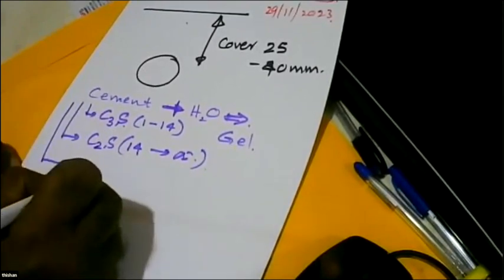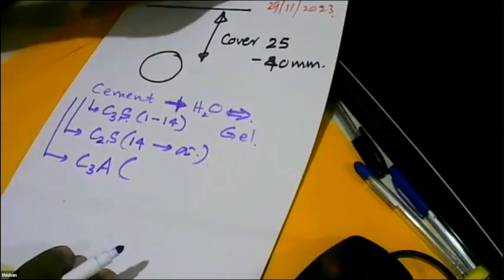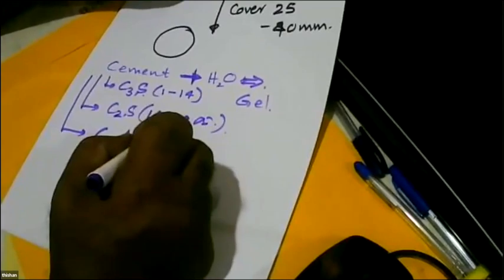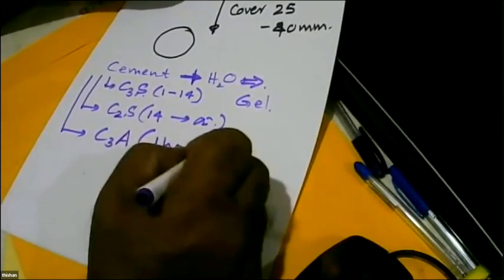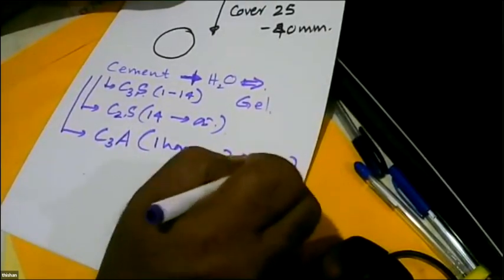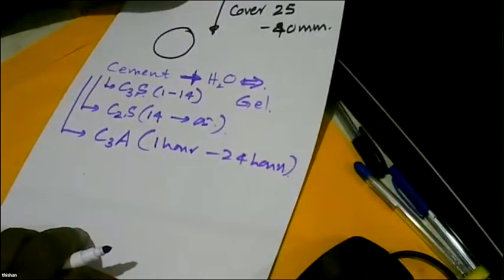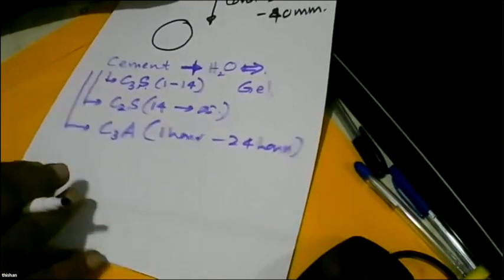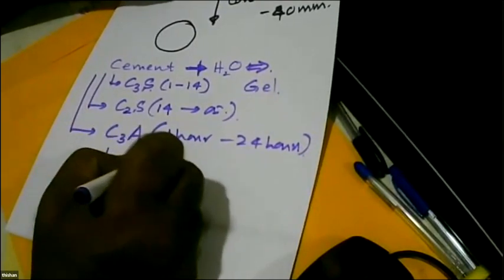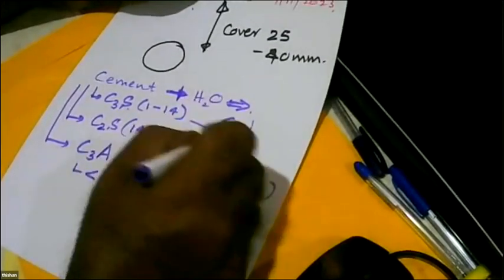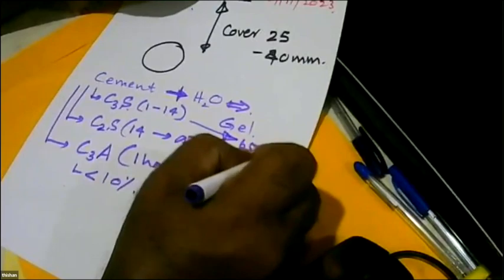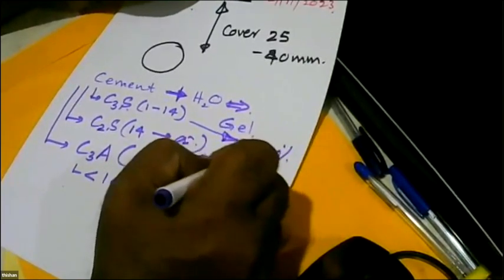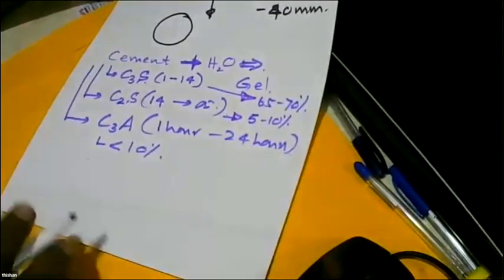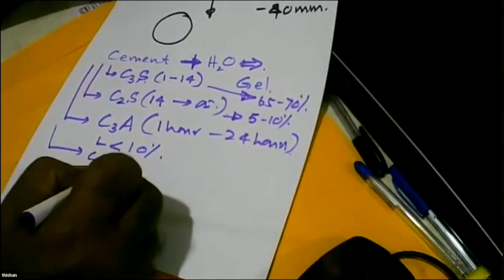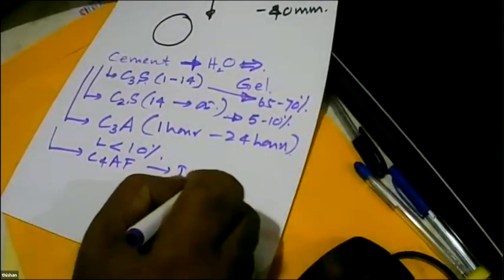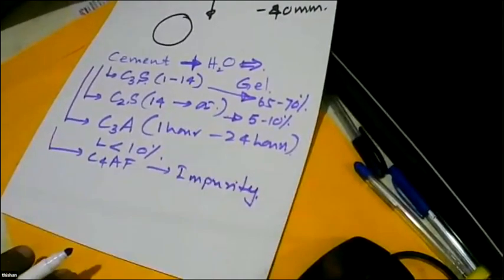Then we get tricalcium aluminate. Very rapid reaction, from 1 hour to 24 hours. But the problem is we can't have too much tricalcium aluminate because it can lead to destruction of concrete after a while. So this has to be less than 10%. This can be anything, but generally it's about 65 to 70%. And in modern cement, this is only 5 to 10%. And then you can get tetracalcium aluminoferrite, and that is an impurity that you cannot prevent when you manufacture cement.